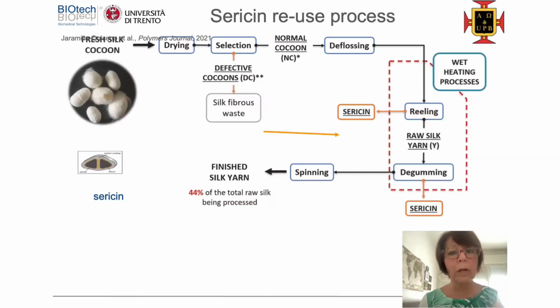Let's go a little bit more into detail into the protocols. For example, what can be done in collaboration with the textile industry. You can see the multi-step recap in the slide. The message of this slide is that each step can produce silk fibrous waste. It can be short fibers, sericin in the degumming bath, or waste obtained during the spinning and textile production. Considering 100% of the material at the beginning, what we can obtain is about 40% of the starting weight.